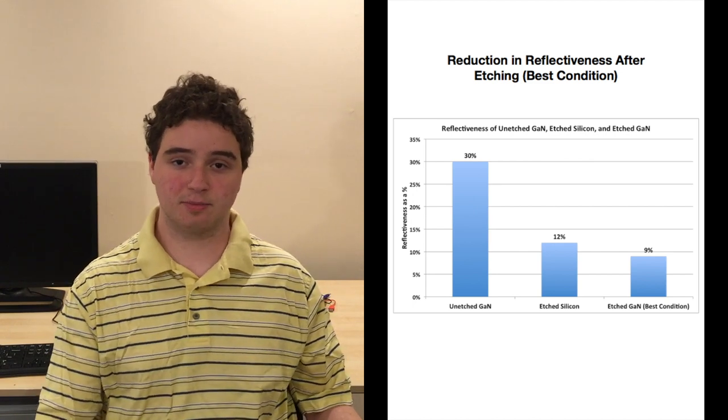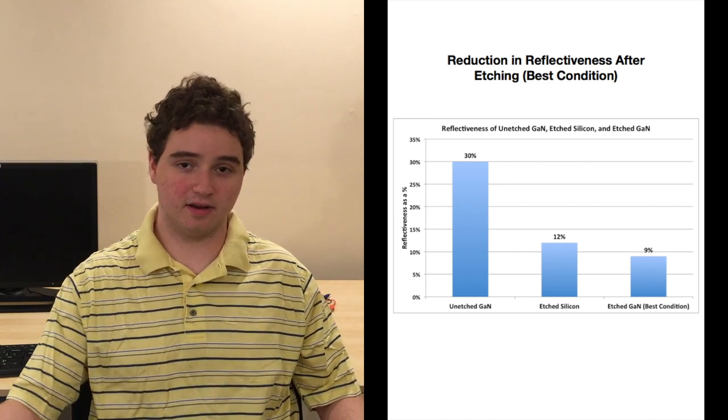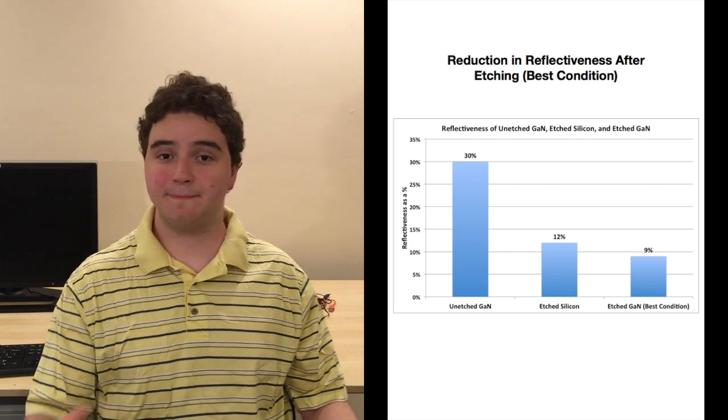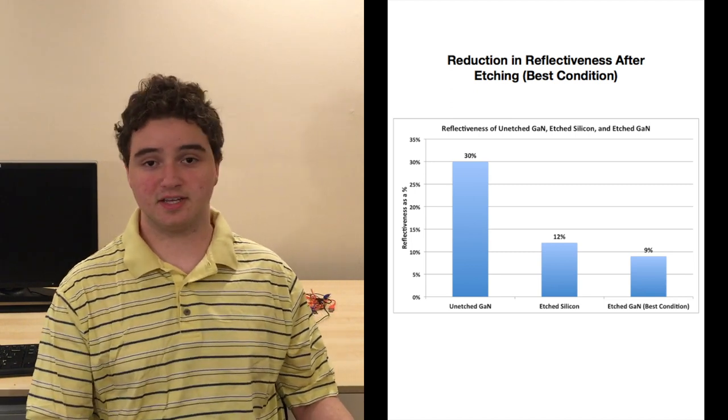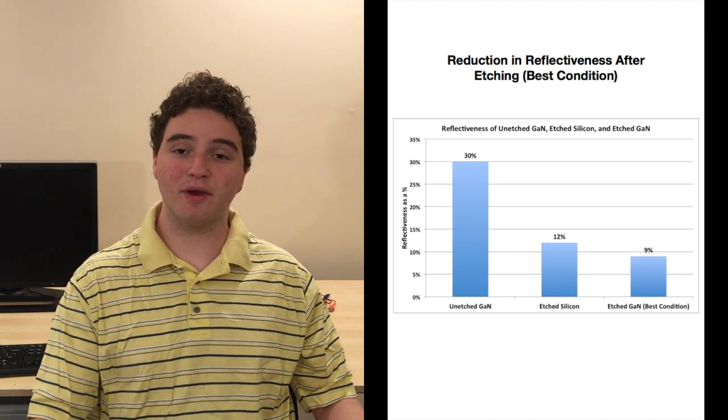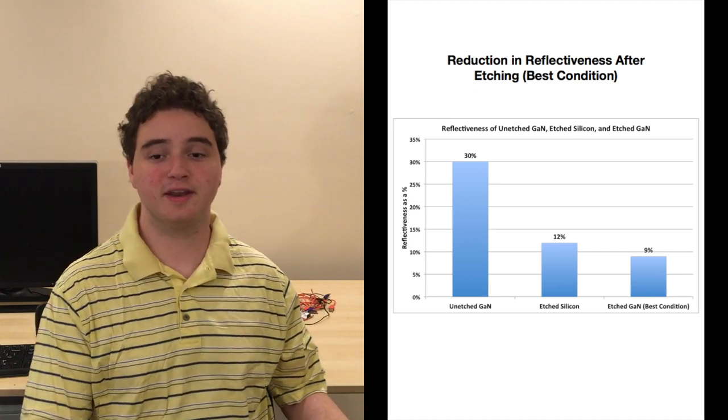So my goal was to bring the 30 percent down to something in the vicinity of silicon. However, under the best condition, the reflectivity was actually reduced to 9.3 percent, which is a huge improvement.